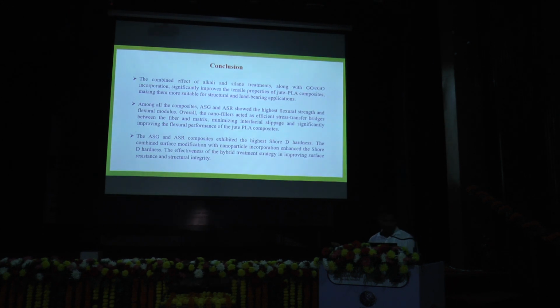In the conclusion part, the combined effect of the alkali and silane treatment along with graphene oxide and reduced graphene oxide incorporation significantly improves the tensile property of the jute PLA composite, making it more suitable for structural and load-bearing